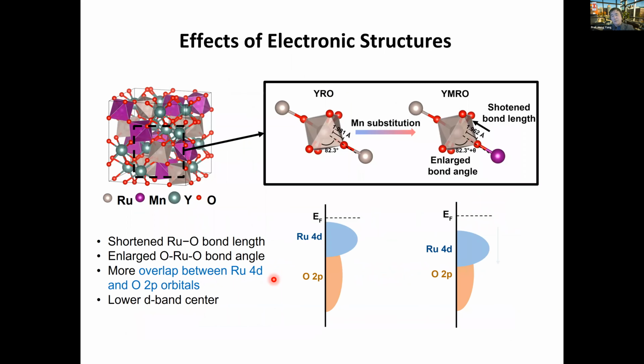So not only one type, but in fact, it's the electronic features that did most of the heavy lifting in this case. So again, this summary is an illustration of the effect we have hypothesized, i.e. this is primarily dominated by electronic structures, and the substitution by the manganese can lead to changes in the bond distance and bond angle of the ruthenium-oxygen bond. In this change we have two factors. One is the shortened bonds, the other is enlarged bond angles.